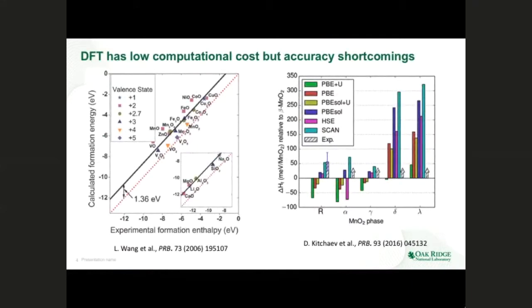So first is the high throughput diffusion Monte Carlo calculations. So the main motivation for doing this research is that when we look at the DFT calculations for the formation energies, or when we just basically compare the different polymorphs of a compound, which is in this case manganese dioxide, we are seeing that there is this kind of shift between the calculated and experimental formation energies, and not all the DFT functionals are really successful in getting the right energetic ordering between the manganese dioxide compounds in here.